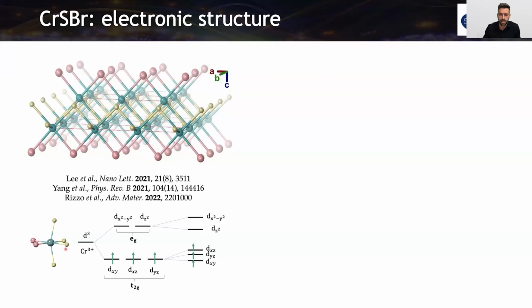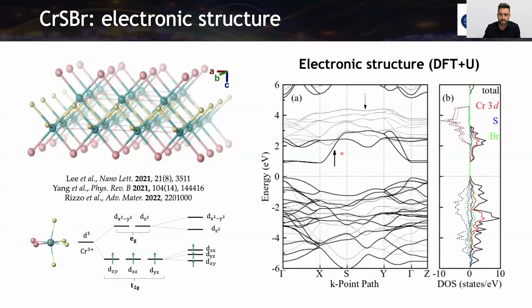This is just a crystal field representation. We are taking now one chromium, and it has this distorted octahedral. This is the B axis in the material. This one is here in Z. And with this, we can have the crystal field splitting. So we have 3 electrons that are making a spin of 3/2, and we have empty eg orbitals. This is reproducing the electronic structure.